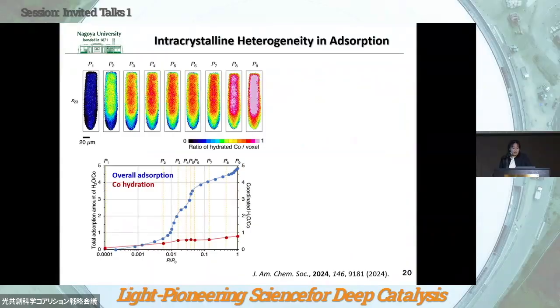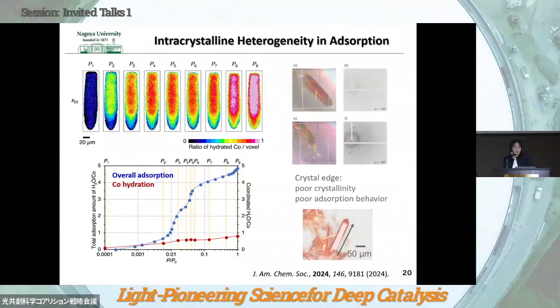And we successfully prepared the isotherm for the cobalt hydration for the first time. So overall adsorption, which is a summation of the physical adsorption and chemisorption, can be measured by the conventional quantitative method, but we can't see the adsorption for cobalt hydration at a particular point in the crystal. So the CT imaging first provided us this kind of hydration isotherm in a real single crystal.